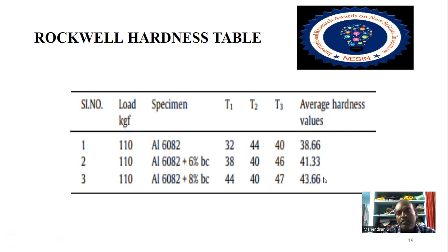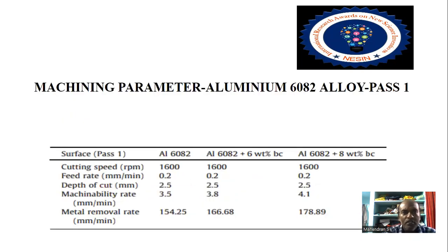38.66 to 43.66. So mixing of the reinforcement material, boron carbide, plus monolithic material, aluminum. This composite material, aluminum 6082 plus 8% of boron carbide, in the third row, and this composite material has better hardness values. It is the first conclusion point.